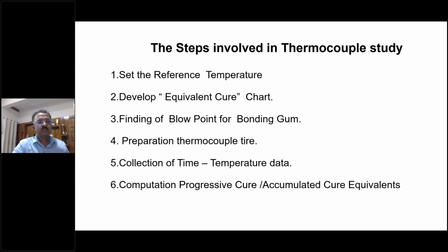So the steps: you set up a reference temperature, maybe 125 degrees centigrade, the normal temperature of retreading, and develop an equivalent cure chart, and find the blow point of bonding. The blow point is the point at which the porosity is seen. Then make a thermocouple tire, put it in the chamber, take the time-temperature data, and from that data we can work out the progressive cure, or cure equivalence.